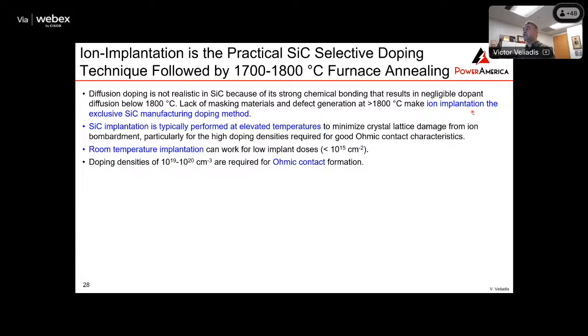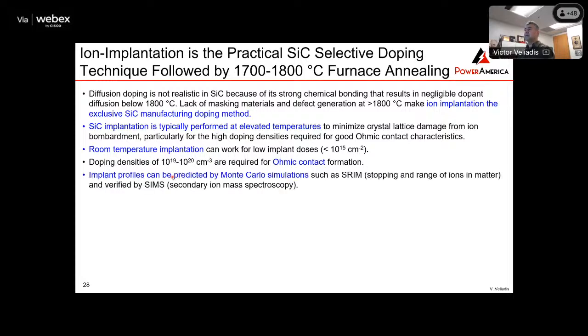Doping densities for ohmic contact formation: you need to have very highly doped contacts in silicon carbide in order to put down the metal and create the ohmic contact. So the doping densities are very, very high for that. You can use Monte Carlo simulations to basically simulate your implantation, get some idea of how to design it.